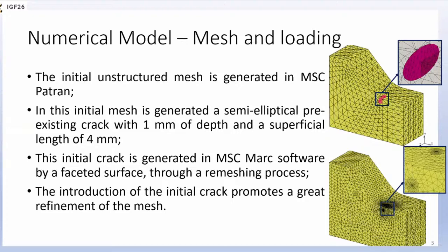The crack growth uses automatic remeshing techniques over unstructured meshes of tetrahedral elements. Residual stresses are accounted for using a superposition technique. The initial unstructured mesh is generated in MSC Patran. In this initial mesh a semi-elliptical pre-existing crack is generated. This initial crack is generated in MSC Marc software by a faceted surface through a remeshing process. The introduction of the initial crack promotes a great refinement of the mesh.